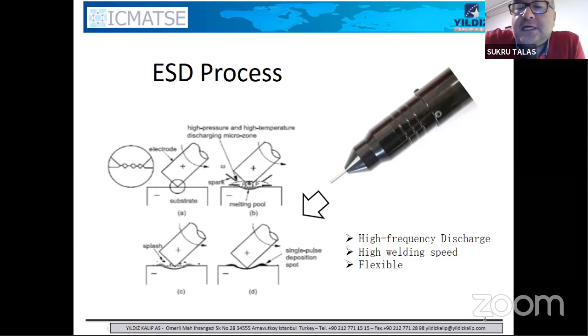You may use tungsten carbide. As long as the electrode is conductive, you may use different types of materials to coat the surface. You can coat the surface of 2379 steel with tungsten carbide, titanium carbide, plus titanium diboride. So you can have a very hard surface, hard facing, by alloying the surface. We have two parameters in this process. The first one is frequency, how often you create an arc, and the second is current. With the current, you can determine the thickness of the layer. With the frequency, the amount of deposition on the surface.